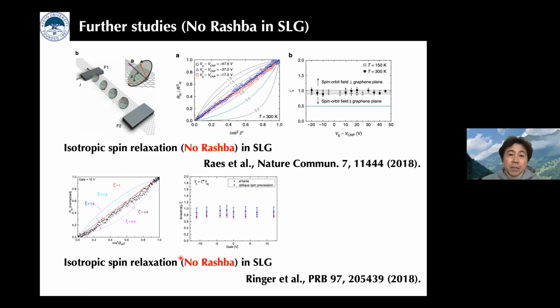Soon after that, a group in Barcelona, Sergio Valenzuela's group, published a follow-up study of our work. In that work, they reported that no Rashba effect exists in single-layer graphene, even though the spatial inversion symmetry is broken. They established an oblique Hanle technique, and by changing the external magnetic field angles they observed saturated spin signals. From this fitting, they concluded that the spin lifetime anisotropy does not exist, meaning the out-of-plane spin lifetime and the in-plane spin lifetime are the same. So this is compelling evidence of no built-in Rashba effect in single-layer graphene.